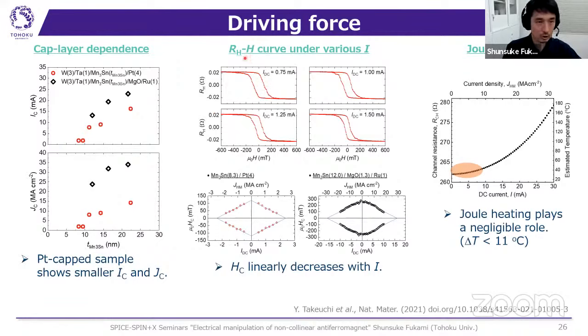And next, we studied the RH loops under various DC current. We measured RH loops for different DC current, and we plot the observed coercive field as a function of the applied current for the two systems with different cap layers. And we observed a linear change in the coercive field, which means that some current-induced effect modulates the coercive field. If the Joule heating were dominant, a non-linear relation would be expected, but a linear relation is observed. So this means that the current-induced effective field should be dominant for this observation.